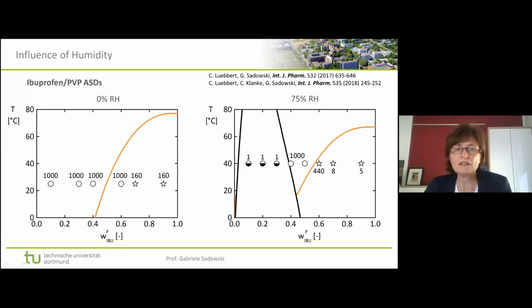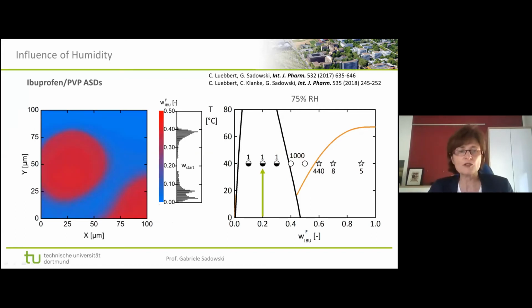And then we did a Raman spectroscopy. This is a confocal Raman spectroscopy, so we could make a scan here. This is in micrometers, so this is a 100 by 100 micrometer scan. And the API concentration is color coded. So that means red means high API concentrations, blue means low API concentrations. And you could easily see that there is a demixing. You could even see how big the droplets are.